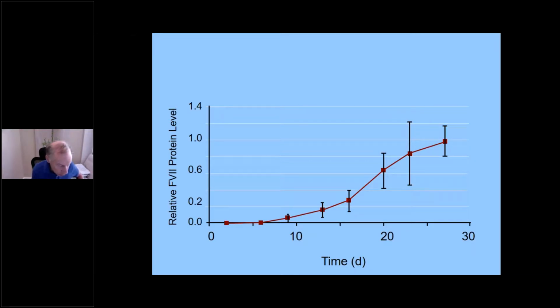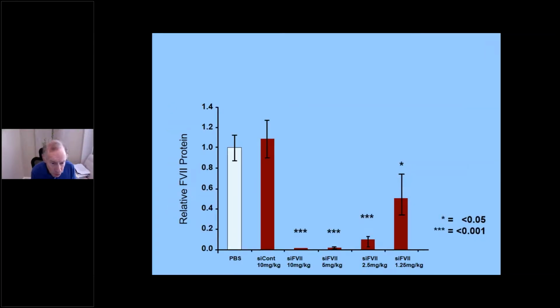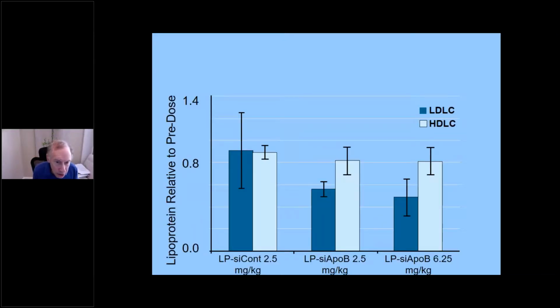And you can also get a dose response curve, which is shown on the next slide, where you can knock down factor 7 as you go from 1.25 mg per kg to 10 mg per kg. You can get complete knockdown. And you could even theoretically treat diseases like that shown on the next slide. Like if somebody had heart disease, you could knock down LDL cholesterol to a high degree. If you look at the 6.25 mg per kg, say somebody had a 300 LDL cholesterol, you'd knock it down to under 200.